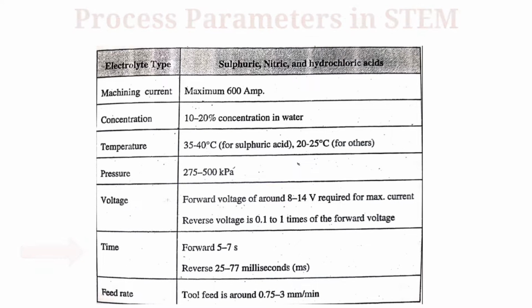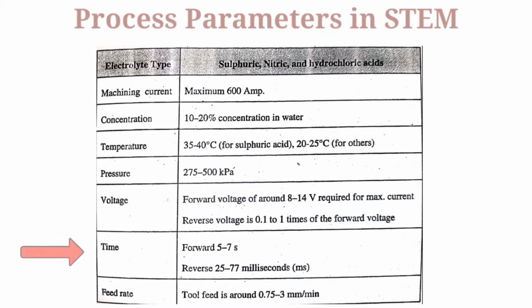Voltage should be a forward voltage of around 8 to 14 volts, as required for maximum current. Reverse voltage is 0.1 to 1 times the forward voltage. Next is the time. For forward action 5 to 7 seconds and for reverse action 25 to 77 milliseconds. Next is the feed rate, that is tool feed is around 0.75 to 3 mm per minute.